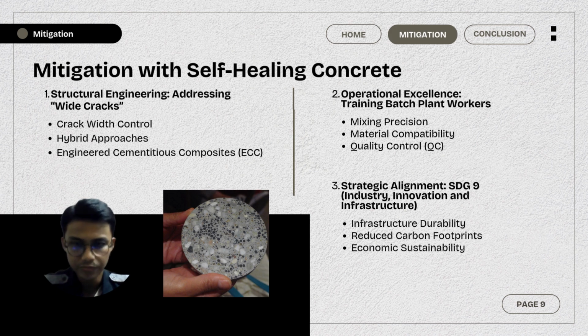Number 2, operational excellence, training batch plant workers. The effectiveness of self-healing concrete is highly sensitive to the mixing process. Improper handling can destroy capsules or render additives ineffective. Firstly, mixing precision. Educate on the sensitivity of autonomous additives by ensuring microcapsules are not crushed during the mixing phase due to excessive shearing or aggregate size.